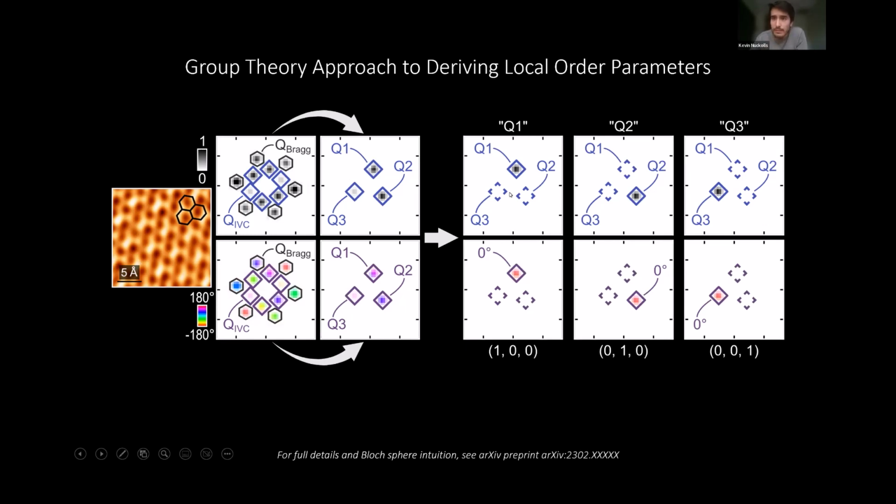But there's one really major problem with this: these local order parameters have fewer symmetries than the graphene lattice. Particularly, the C3 symmetry of the graphene lattice is not preserved in these local order parameters. C3 symmetry about a hexagon center leaves the graphene lattice invariant, but if a state itself breaks C3 symmetry spontaneously, we would never be able to tell, because under C3 rotation of the STM image, the FFT has its peaks permuted.